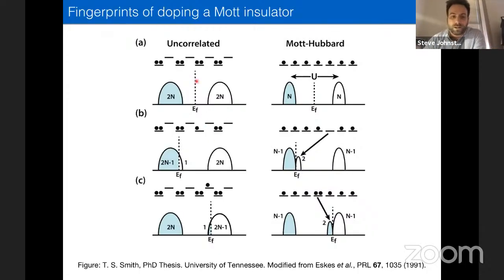Yeah. So to remind you, in a band insulator, what you expect to have happen is you're going to have bands with spectral weight 2n. If you have n atoms in the system, there will be a filled band with spectral weight 2n, a gap to an empty band with a spectral weight of 2n, and a Fermi energy located between the two. And when you dope the system, remove electrons from it, we get these rigid band pictures that we talk about in solid state physics classes. You remove some of the spectral weight and the Fermi energy or the chemical potential just swings down into one of those bands. This is very different from what happens in a Mott insulator.